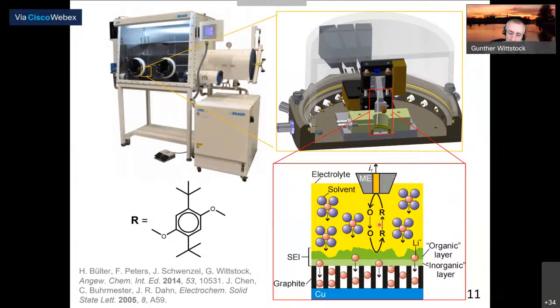So in these studies, we use the feedback mode. We add a mediator in organic solvents under glove box conditions. This molecule has turned out to be extremely stable and extremely good for that purpose, so much better than other mediators. So we prefer that a lot.